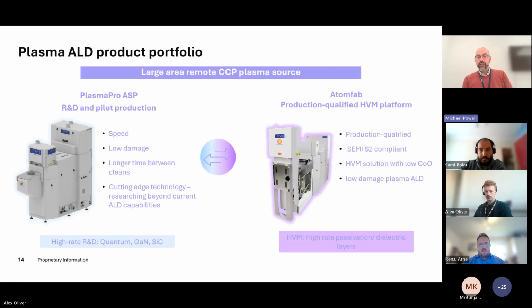So that was quite a quick overview of where we sit as Oxford Instruments itself, and specifically plasma technology. But where we were really brought into the project was to talk about atomic layer deposition. Within silicon carbide, for a long time it's been a thermal oxide route that has delivered the gate dielectric, and that has some drawbacks in terms of carbon at the interface, and in terms of what that means for the quality of the device, the switching speed of the device, and how much you can actually put through the device before it breaks down.